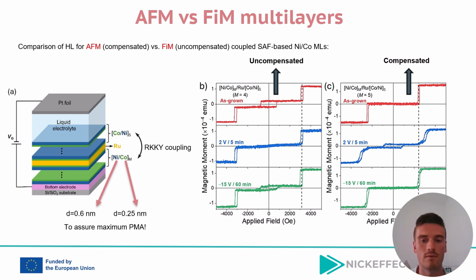Starting from the as-grown state, and then following by the application of negative and positive voltage, the uncompensated system with 4 cobalt-nickel multilayer repetitions in figure B shows a net magnetic moment, while the compensated system in figure C with 5 cobalt-nickel repetitions shows a respectable near-zero net moment.